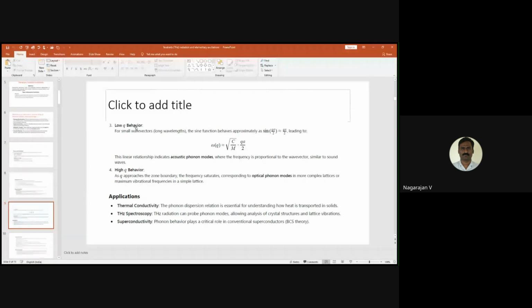Low-q behavior determines frequencies proportional to the wave vector, similar to sound waves. High q behavior, which approaches the zone boundary, has frequency saturating, corresponding to optical phonon modes in a more complex lattice, and maximum vibrational frequency in a simple lattice system. So this indicates such behavior of the phonon.